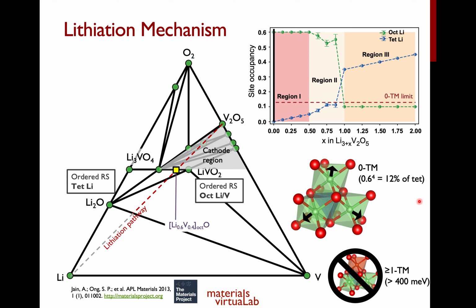Now, if we actually look at the one transition metal or even more than one transition metal tetrahedral sites, basically all the site energies are at least 400 meV higher. So we are not going to think about all these sites. Those are really much more unfavorable than our zero transition metal tetrahedral sites.